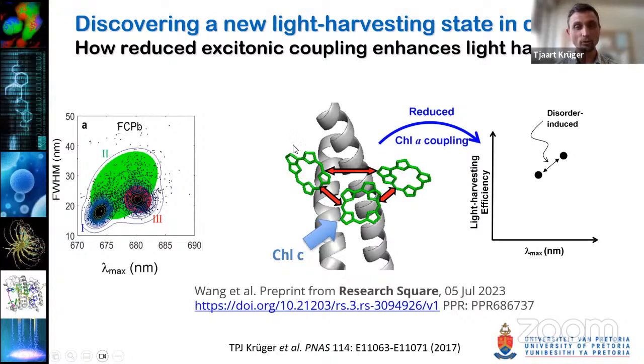And in LHC2, this coupling is extremely strong. This coupling has to be broken in diatoms. And the coupling is broken by diatoms having this chlorophyll, which is chlorophyll A in plants, replaced with chlorophyll C, which breaks this excitonic coupling. So this actually confirms the model and the results that we proposed 5-6 years ago.